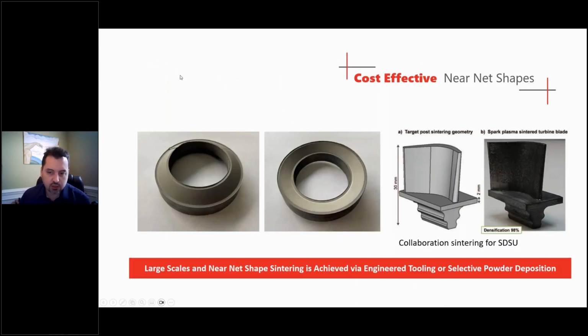So near net shaping, one of the additional benefits. I touched on the binder jet and a little bit of the tooling on the net shaping, but it's just, again, a recap that we can actually do quite a bit. This is a straight out of the SPS part. You can see a little bit of flashing here. You can see just a little bit of parting materials from some of the separation foils that we need to use. But other than that, you'll see the very fine surface finish, very high tolerance. So your surface finish matches your tooling. In this case, this part, if it's made out of a more expensive material, will have significant savings in lost material and in reduced secondary machining. And so a lot of work is going on in just, again, the net shape or near net shape manufacturing. And that's one of the main advantages to SPS as well.